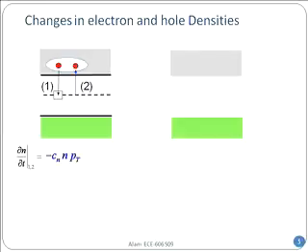Look at that n. n is the number of electrons. If we have more electrons, of course it will get captured more. p_t is the number of traps that are empty. Of course it has to be empty, otherwise how is it going to catch any electron? And C_n is the capture coefficient, proportional to the velocity, because if the electron is running around quite a bit, then the probability of getting captured is more. So it is proportional to the thermal velocity, which you saw in the last class.